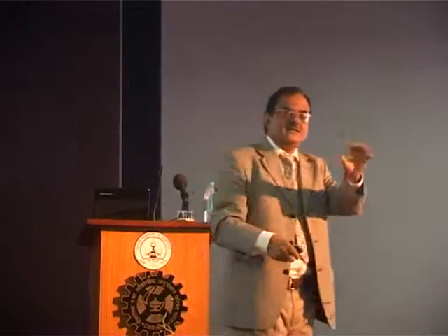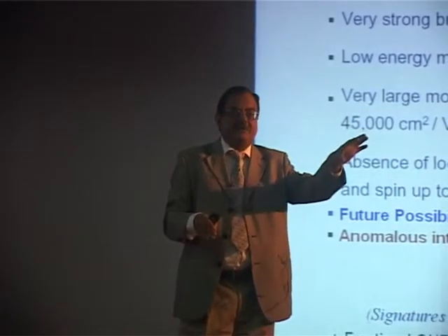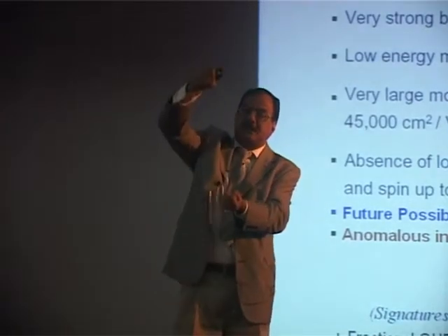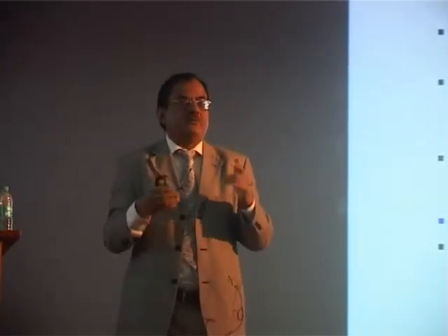And that has also been seen last year in graphene. And now, this effect has been seen at room temperature. All the quantum Hall effect experiments are done below 4 Kelvin, helium temperature. In this material, because of the large spacings between levels, you can see this effect at room temperature. So you are seeing beautiful quantum phenomena at room temperature.